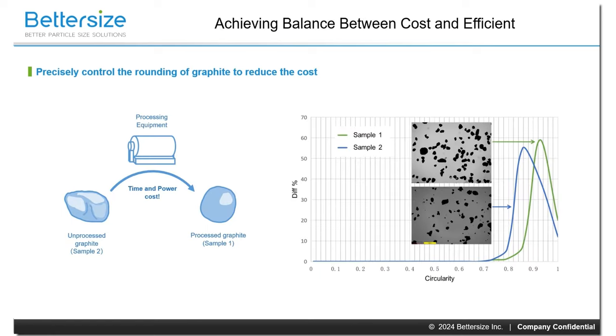This is an application case of anode material rounding process. As the picture on our left shows, the graphite needs to be rounded, but the process needs to be stopped at a suitable point, otherwise the over-rounding will cause waste of cost and time. For some country or region, the standard value is average circularity larger than 0.9.